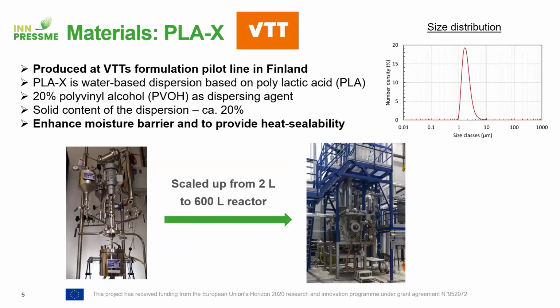So a little bit of background of the material. The PLA-X was produced at VTT's formulation pilot line, and PLA-X is a water-based dispersion, which is based on polylactic acid, and polyvinyl alcohol is used as the stabilizing and dispersing agent. PLA-X was used in this multi-layer packaging to enhance the moisture barrier of the packaging and also to provide heat sealability to the multi-layer. And we demonstrated in this project that we could scale up the production of this PLA-X dispersion from only 2 liters in lab scale up to 600 liter reactors. The final material that we got out was 250 kilograms of this dispersion in only one batch. And it was done in a one pot reaction, so we can do the polymerization and also the dispersing step in the same reactor.